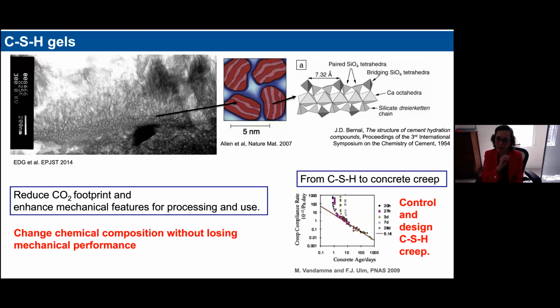So understanding the physics of how this precipitation and gelation works has consequences not just for the strength of the material, but for the durability of the material and of the infrastructure. For example, one proof of that is that concrete and cement are solid materials that are characterized by creep. And these are the experiments of my colleagues at MIT that measured some years ago the creep compliance rate, so the evolution of the flow properties, also the deformation rate in a material that is actually solid.